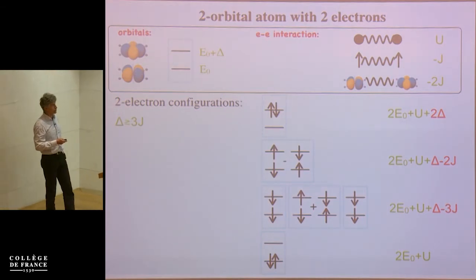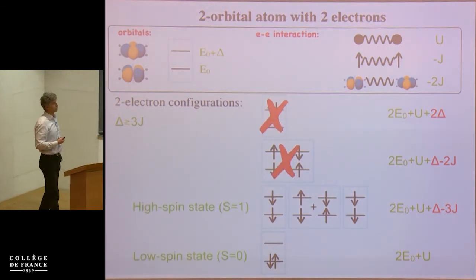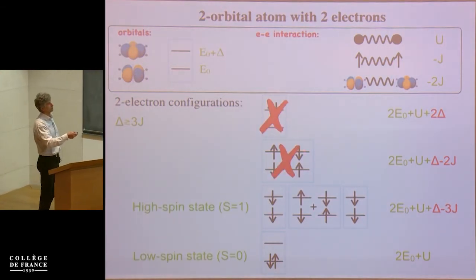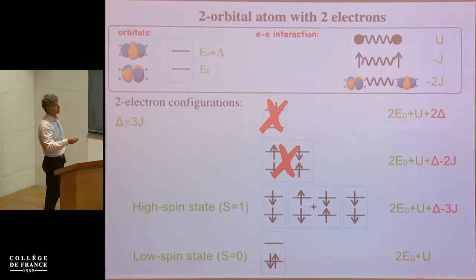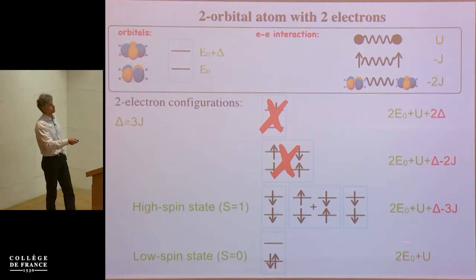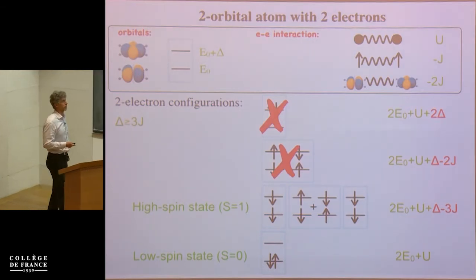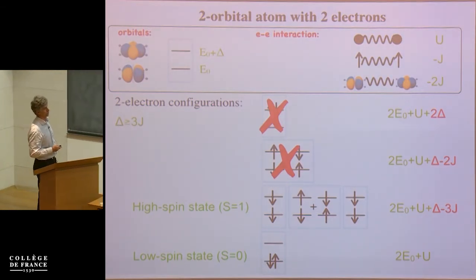For the purpose of our further developments, I will forget about these excited states, and I will focus on the situation where the energies of these two states, the low spin state and the high spin state, are not very different from each other. This means the crystal field should be approximately equal to 3 times the Hund's coupling.